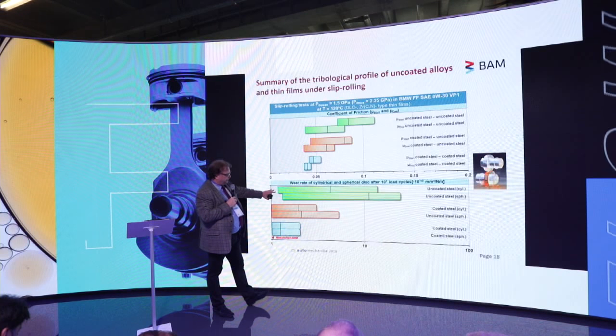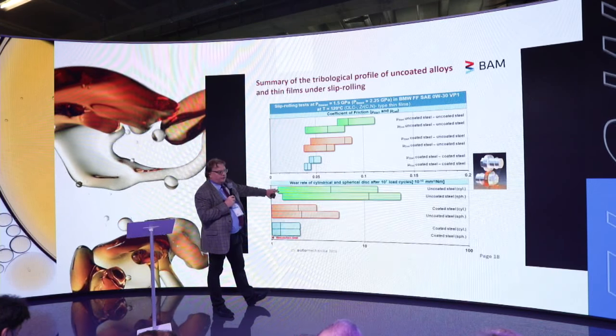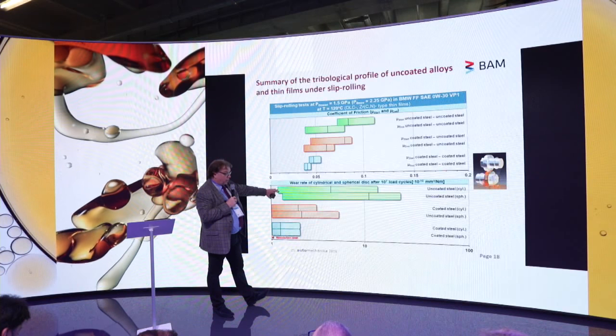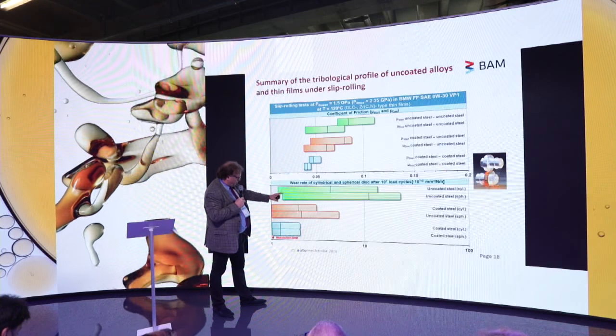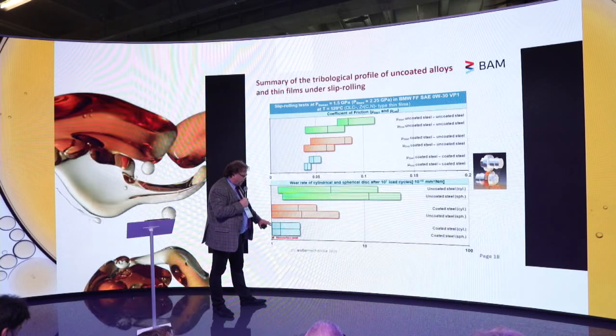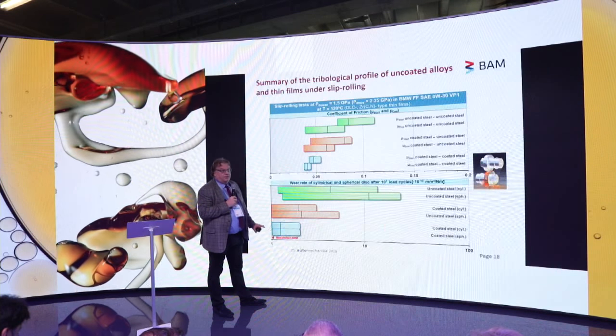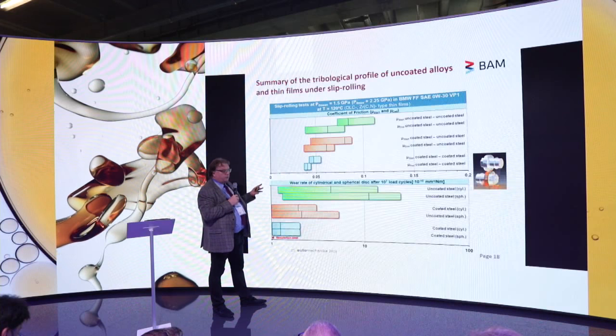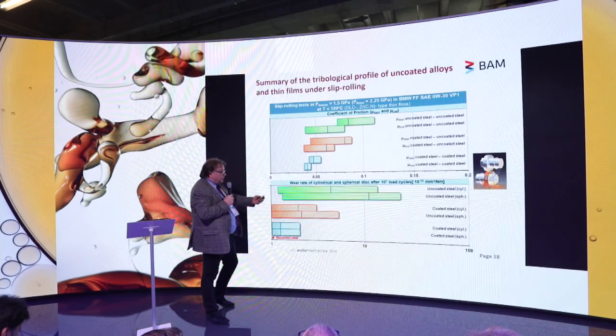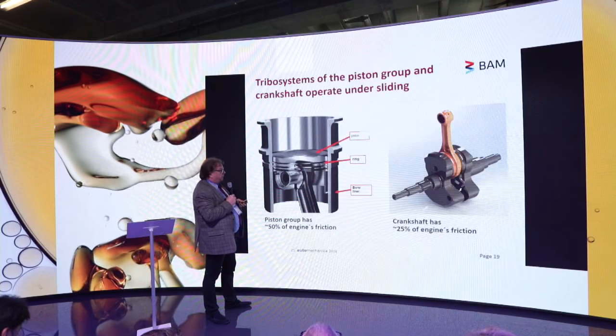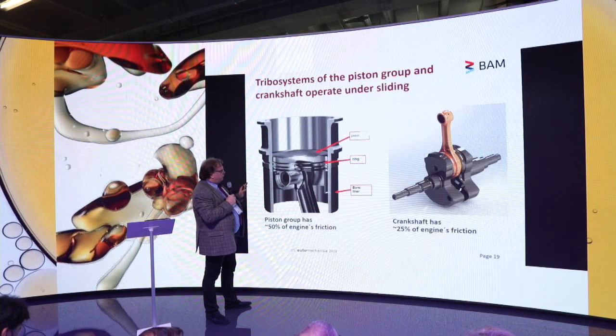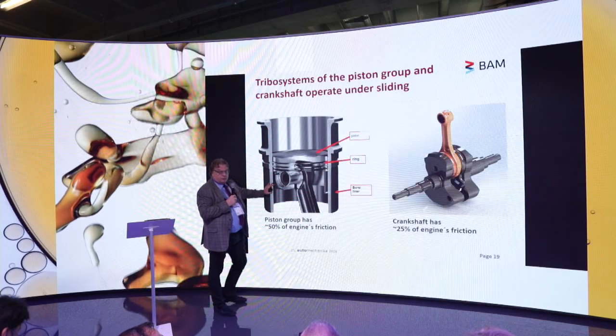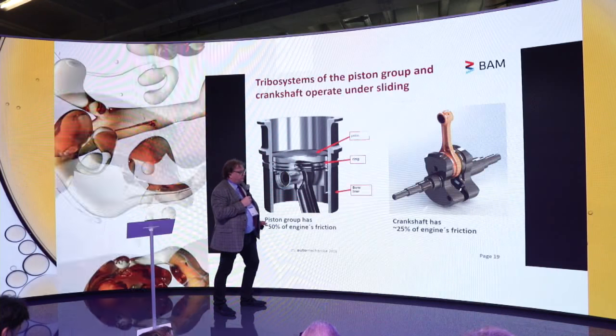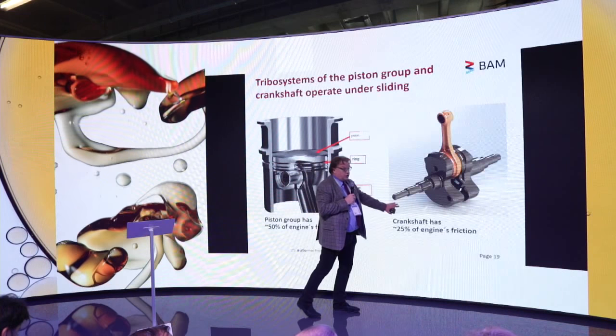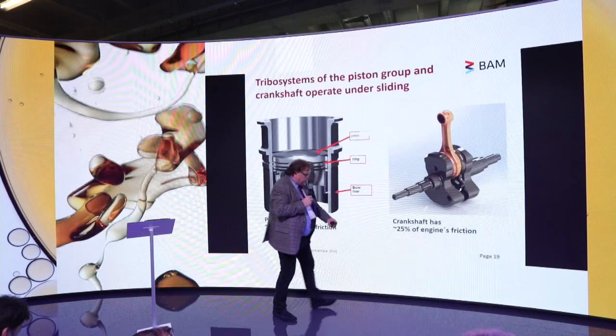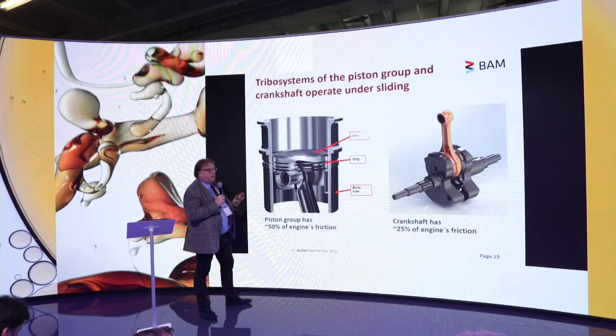Same for wear. You can find alternative steels with very, very low wear uncoated. Now you coat, wear goes down, and when you coat both, zero wear. This was now for gears and for slip rolling contacts. The other two main systems, the piston group, you have 50% of the friction, and the crankshaft, 25%. All sliding contacts.